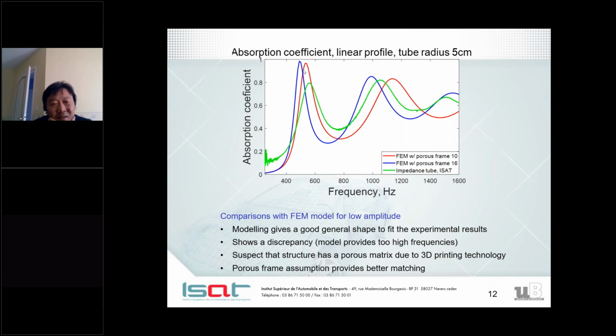And here is the result of simulation compared to experimental results in green, but accounting for some microporosity effects here. But here, of course, it's difficult to correctly predict the experimental curve because at the moment we don't have a clear idea about the properties of the microporosity. But this simulation was just to show that with accounting for microporosity, it was possible to have a much better match between experimental and theoretical results.